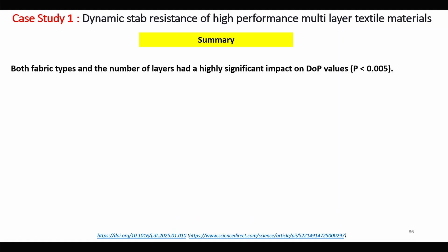So, the basic summary here is that for both fabric types, 2D and 3D fabrics, the number of layers is highly significant, in that the higher the number of layers, the lower the depth of penetration. So, number of layers has very high significance on the depth of penetration.